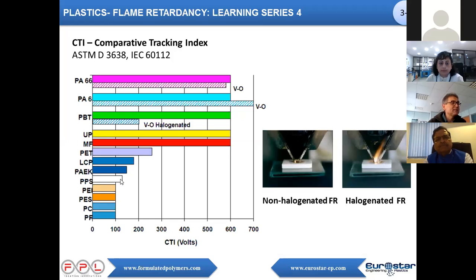You can have a very good material but with a very poor CTI. For example, PPS is a very high thermal material, but you never see it close to the arc because it's very poor in CTI. Same thing, you never see an MCB closure for a contactor or a circuit breaker in polycarbonate, because it's a good material but very bad for arcing. Then you see in this chart that materials that behave very well are polyamide 6 and 6,6. It's no chance that many materials for electrical and electronic application have been made for more than 30 years in nylon 6 or 6,6, because inherently it has a very good resistance to the arc.